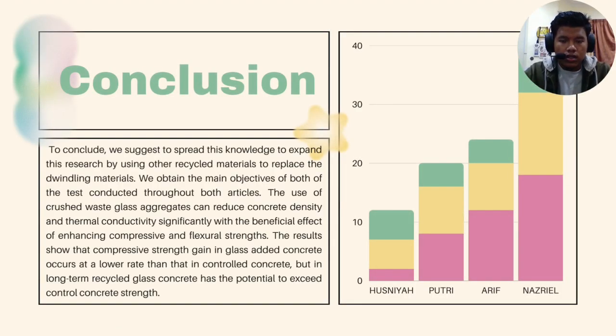Lastly, for the conclusion, we suggest to spread this knowledge and expand this research by using other recycled materials to replace the dwindling material. We achieved the main objective of both tests conducted throughout both articles. The use of crushed waste glass aggregate can reduce the concrete density and thermal conductivity significantly, with the beneficial effect of enhancing compressive and also flexural strength.